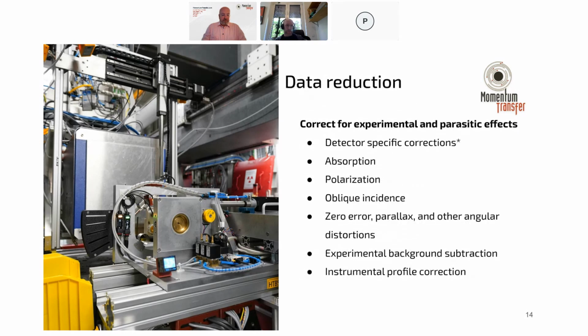So there's a lot of data processing that gets coupled into this. Because we use large area detectors, we do a lot of corrections for the geometry of the detector. We correct for absorption into the detector pixels, polarization of the beam, and oblique incidence. We also correct for offset errors. So for instance, with laboratory systems, you sometimes have a height error because it's very difficult to control the exact height of the sample on your sample holders.